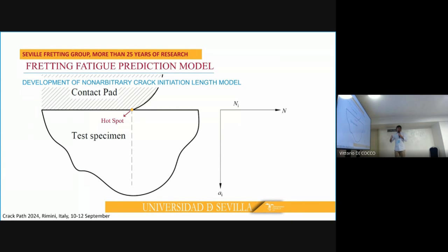Here, there is a very brief explanation, a simplified explanation of the model. First, you need to obtain a hot spot at the contact surface. Then it is assumed that the crack initiates and propagates along a line starting from this hot spot. For the time being, we assume that this line is perpendicular to the contact surface. For a certain crack initiation length, you can obtain the number of cycles required to initiate it. Then, using fracture mechanics procedure, you can obtain the number of cycles required to propagate that initiated crack until the final fracture. Adding these two fatigue lives, you can obtain the total fatigue life for this assumed crack initiation length.